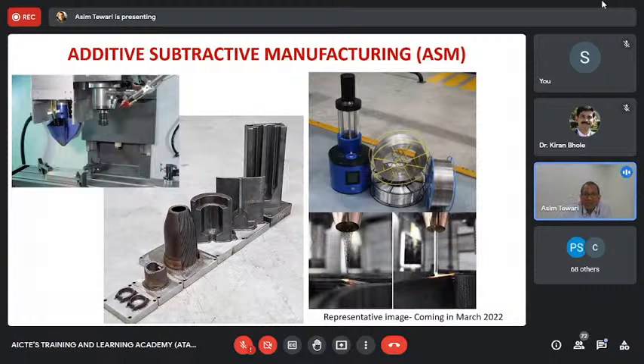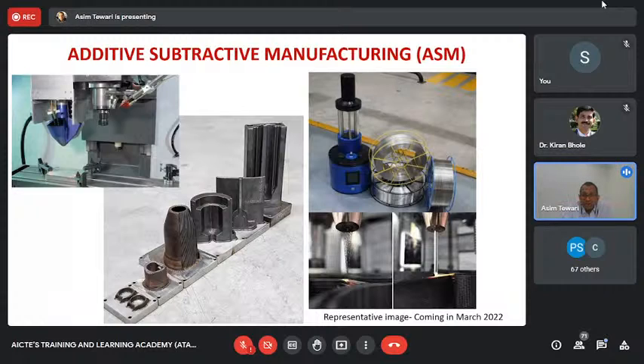And the beauty about wire feed is that wires have lesser surface area, at least 5 to 6 orders of magnitude lesser, actually 10 orders of magnitude lesser surface area. And because of that, they do not get contaminated by oxygen. So if you are doing powder-based additive manufacturing, you need to create a very high quality inert atmosphere around it. Whereas in a wire feed, you really don't need that, because wire has very little surface area and you can get a very high quality part with very little environment around it. Of course, we will be having an inert environment around it, but what I'm trying to say is that it would not be so much of an issue if we are having a wire.